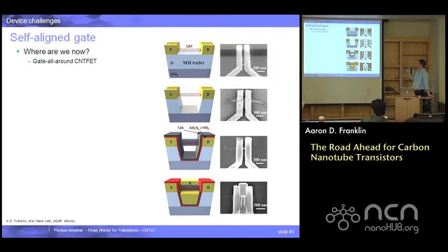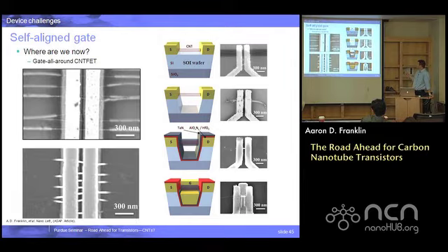So what we did is we decided we want to suspend the channel and we want it anisotropic, but we can't do the dry environment etch. So we used an SOI wafer and made use of the crystal orientation of the silicon, where when you etch it in a wet environment, it will actually etch anisotropically. And the etch that we used was a KOH etch, which we tested the tubes and they survived just fine without degradation. And it enables me to suspend the nanotubes across this channel area where I put the source and drain down first, and they mask it off.